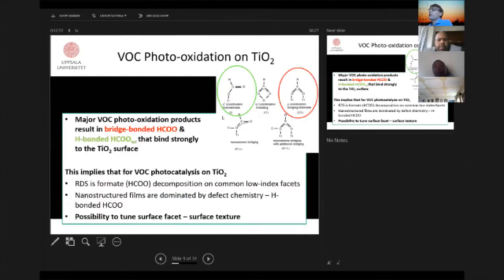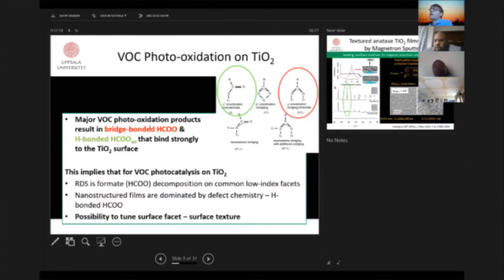To summarize this, we know that in many of these VOC photooxidation products, you end up with small molecules which have a tendency to form these coordinated compounds, which are very difficult to get rid of under the mild conditions photocatalysis is operating under. So knowing the RDS, the rate determining step, and knowing how they form, and the role of defects, which I will not talk about here, you have the possibility to tune the surface facets or the surface texture. And this we'll now discuss.